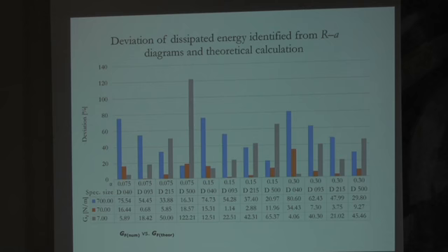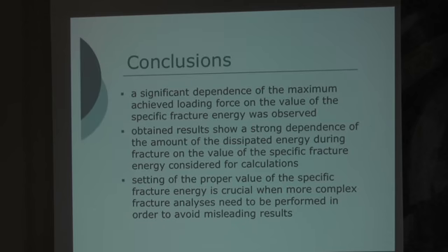So let me conclude our contribution. As I told you, a significant dependence of the maximum achieved loading force on the value of the specific fracture energy was observed. Also, the obtained results showed a strong dependence of the amount of dissipated energy during the fracture on the value of specific fracture energy, which we considered in the calculation.